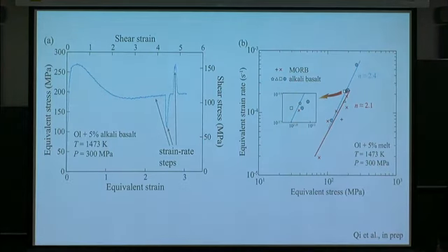Okay. All right, so here's some mechanical data from one of these tests. Again, we hit a peak stress that eventually dies off to some approximate steady state. You can perturb the strain rate, and you get a stress exponent that's something like 2 to 2.5. And I piped up a little bit earlier in the week saying this is relatively consistent throughout all the experiments that are done where we have this in olivine, where we have this melt segregation. I personally don't quite know how to explain it, and I think it's indicative of something interesting. We can talk about that more later.